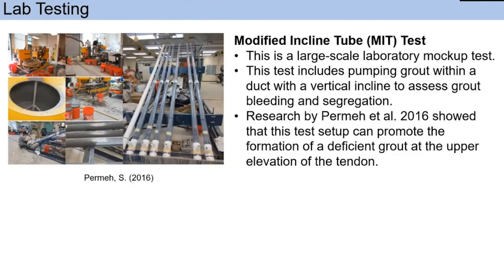This is a large-scale laboratory mock-up test. The modified inclined tube test includes pumping of grout within a duct that is 3-inch diameter and 15 feet long PVC pipes, which is placed at an angle of 30 degrees inclined. The grout material is pumped from the bottom, and the valves at the outlet and inlet were closed sequentially to prevent loss of material. As per research by Permeh, the top elevation showed that the moisture content was greater than 20% and sulfate level was elevated. These research efforts show that this setup can facilitate the formation of deficient grout at the upper elevation of the tendon.